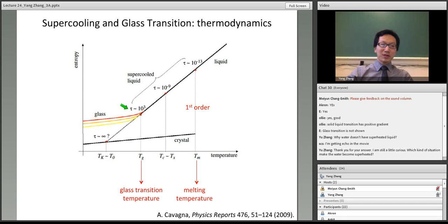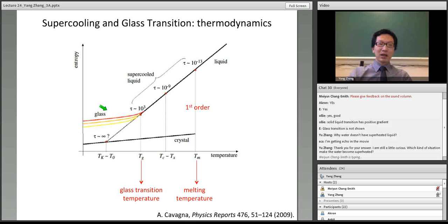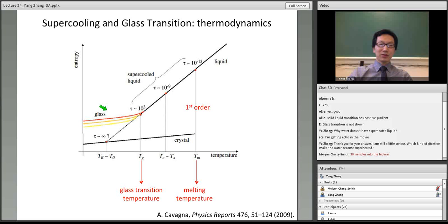But as you can see here, I have several lines near the glass. So it means that depending on your cooling rate, you may end up with a different glass state. So glass is not unique. It depends on the thermal history, how you define the glass transition. If you cool it down fast enough, then you can reach the glass transition at a higher temperature. If you cool it down slow enough, then you can go to an even lower glass transition temperature.